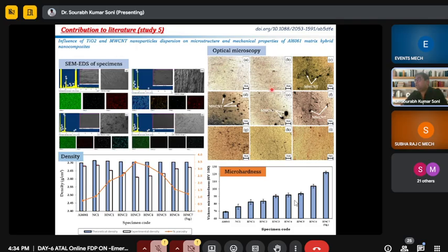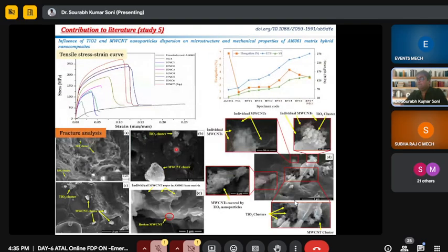This is the optical microscopy, so we can observe the grain refinement also. Here in the squeeze casting sample I have observed very little agglomeration and porosity. So I can say that squeeze casting is a very good approach to fabricate MWCNT TiO2 AA6061 metal matrix composite. And in this specimen, I am getting higher microhardness also. So we can relate this kind of structure-property relationship.